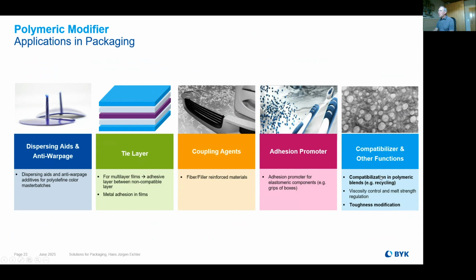So that means if polymers like polyamide and polyethylene, for example, which don't like each other, are in a recycling material, those modifiers still work as a compatibilizer. It can also work as a viscosity controller to improve the melt strength. That might be very interesting for biopolymers. And beside that, the materials are also used as a toughness modifier, for example, in polyamide.